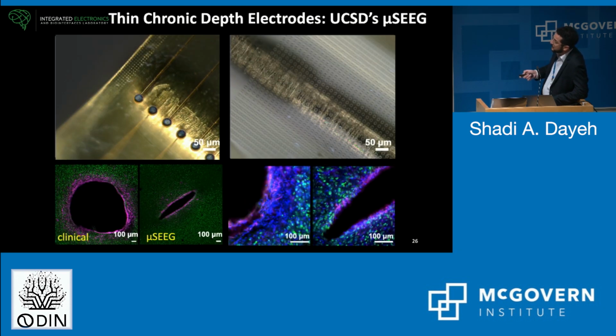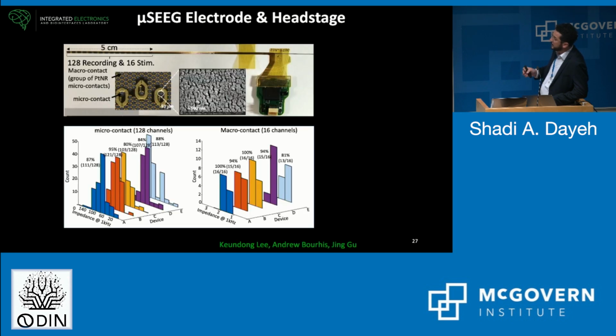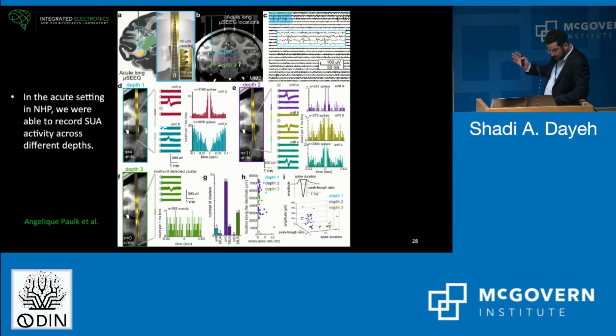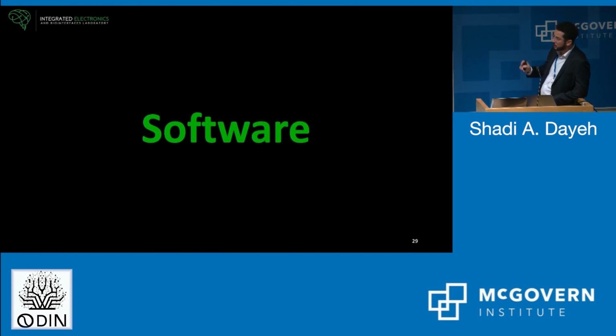numerous. One is that the lesion that it will create is very small. Two, it's very flexible, so one would be able to attain more stable recordings and hopefully carry out these recordings and stimulation for longer durations of time. The electrodes afford clinical monitoring and stimulation with about 16 macro contacts and then 128 channel microelectrode contacts that could be distributed across the whole shaft. We've used those across species, including in humans, and here we're showing one example in the Cash lab where we've recorded single unit activity in the hippocampus in the acute setting.